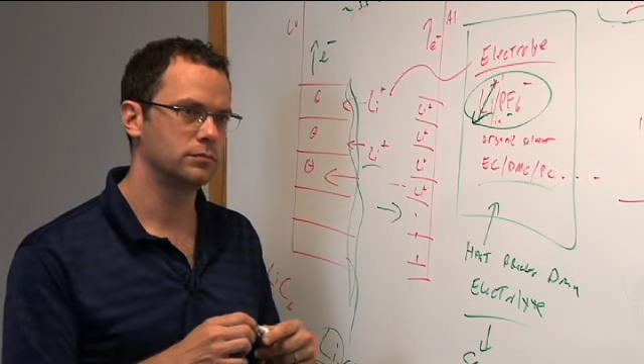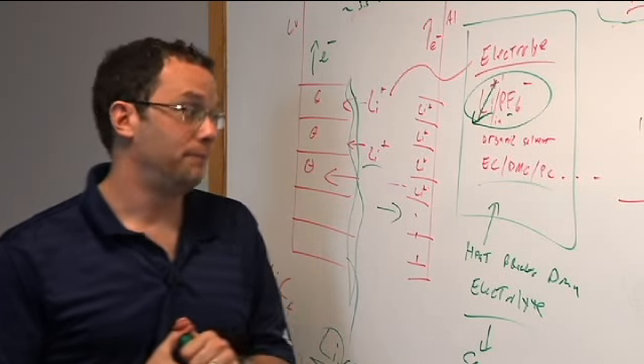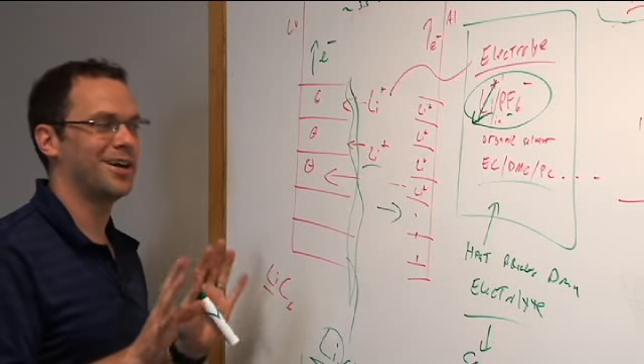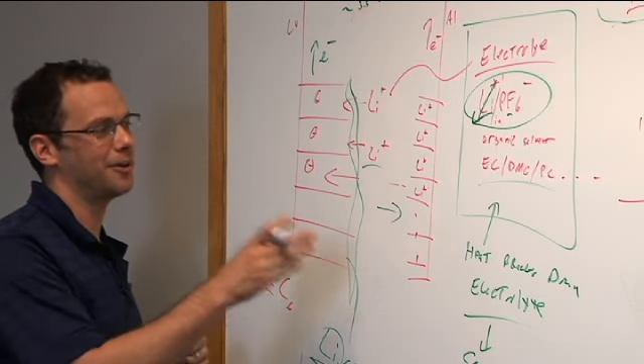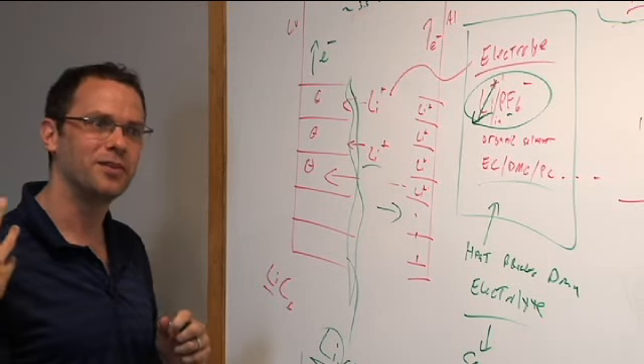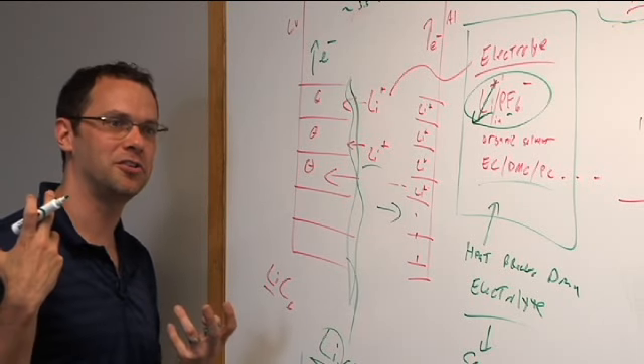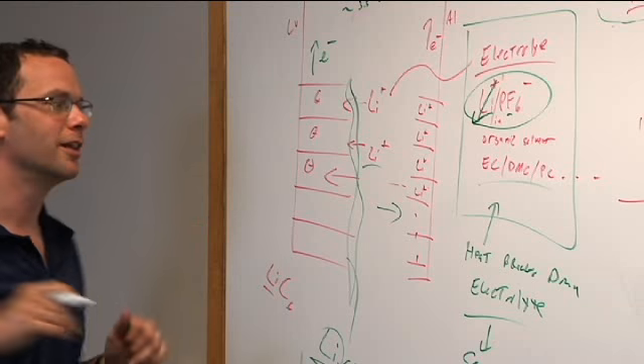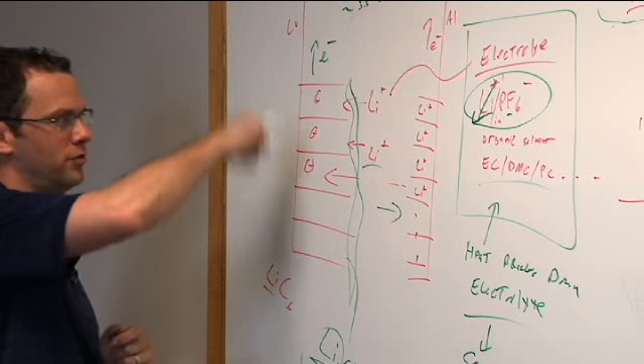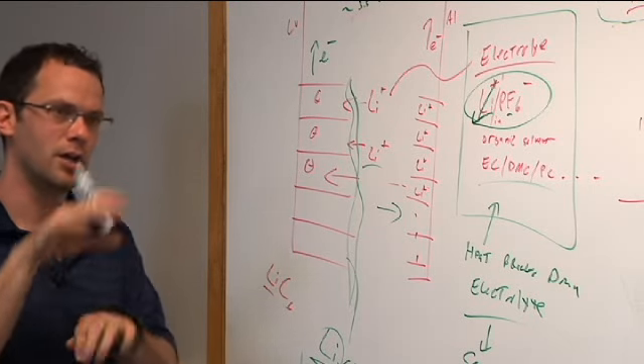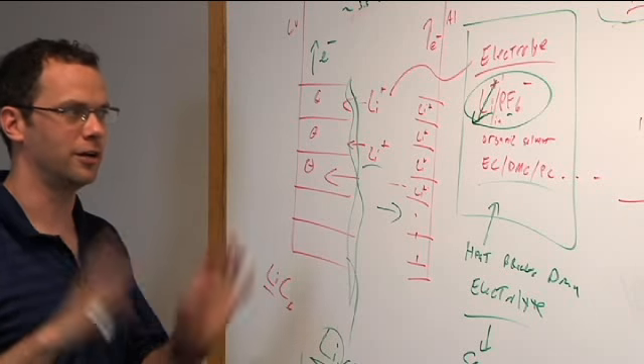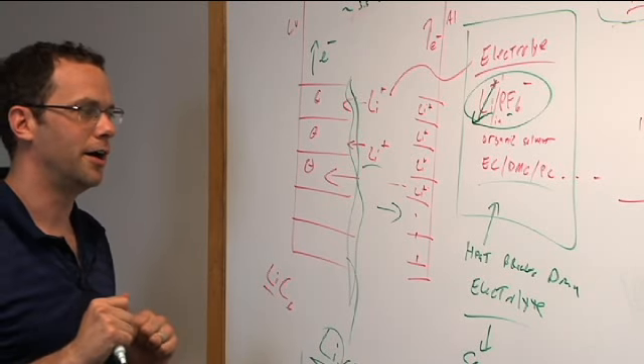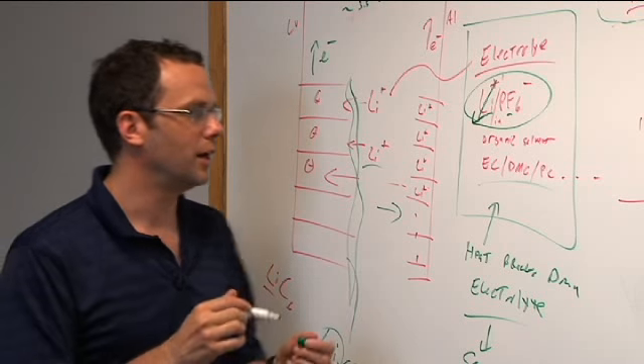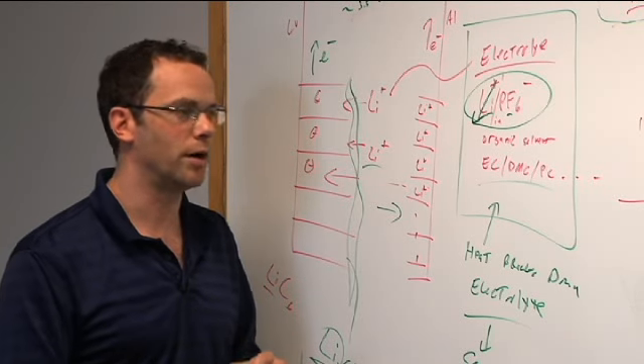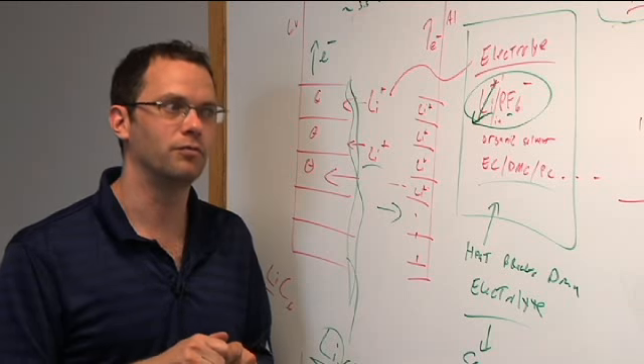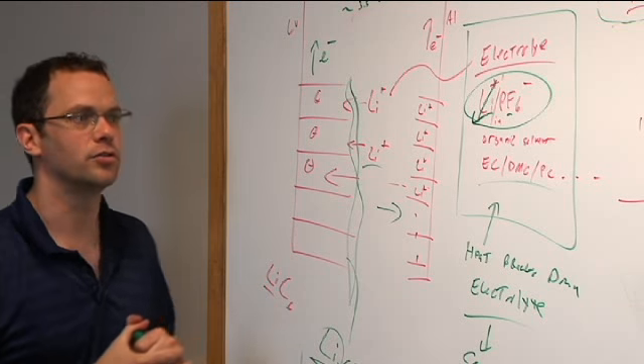So why is it that the cobalt cells kill themselves below a certain voltage? Again, lithium cobalt oxide is a different bag. That material can accept more lithium, but it has a catastrophic phase transition, and it renders itself useless. Lithium cobalt oxide has a structure actually not too dissimilar from graphite. It's got these layers, and you can jam a lot of stuff in there, and it's not so good. If you allow it to go to 0 volts, it probably won't be good at all, period, after that. It's very unusual to be able to resurrect that. You'll screw up the crystal structure.